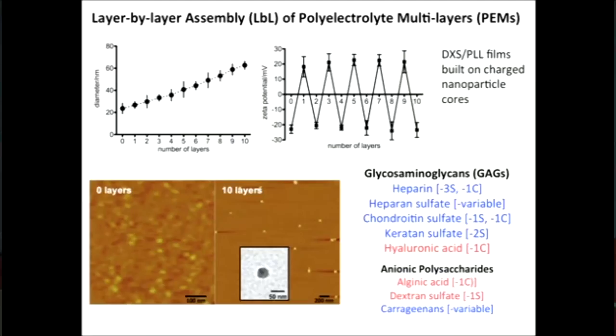imagine. Now, when you're building these films, here's an example of starting with a quantum dot, a tiny 20 nanometer nanoparticle. We chose it because it glows, essentially. We can track it. And we start with something that is 20 nanometers, and we build each layer, and we see that it grows in size, but in a nice linear fashion. That's what a good layer-by-layer film is going to do. And it gets up maybe about 5 to 6 nanometers per adsorbed layer.